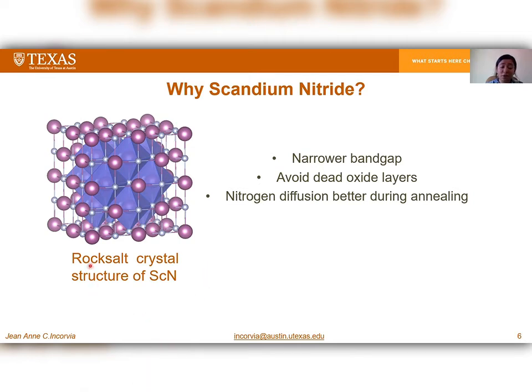Scandium nitride has a similar rock salt crystal structure to that of MgO, but it has an advantageous narrow band gap, which could possibly lead to a thicker barrier with low RA product. Also, there are a lot of dead oxide layers at the interface between MgO and the electrode. So a nitride film could possibly avoid those dead oxide layers. Also, nitrogen diffuses better during annealing as well.